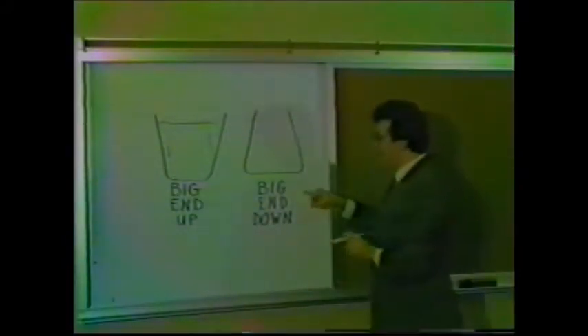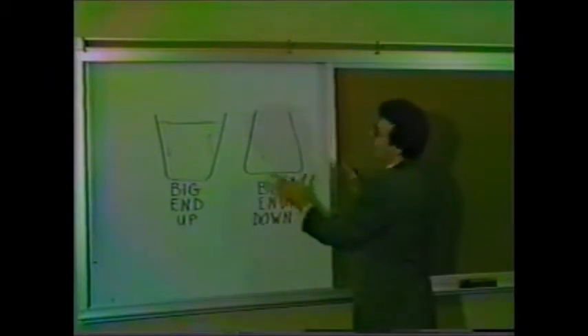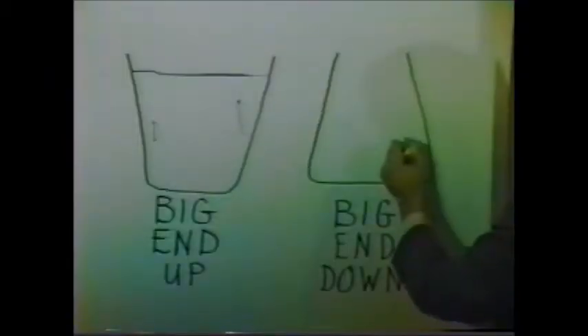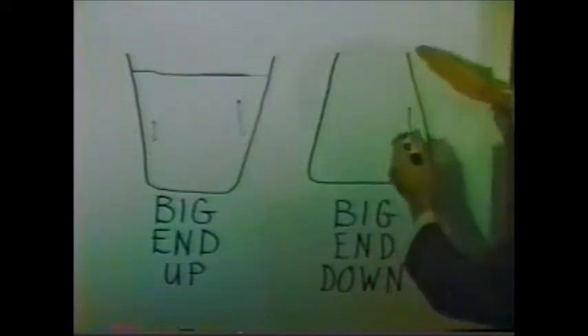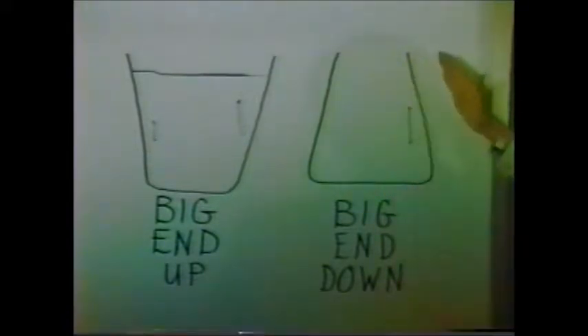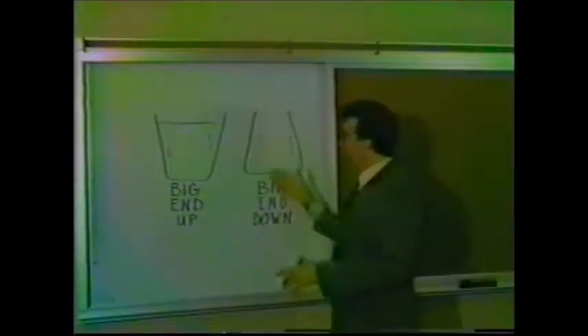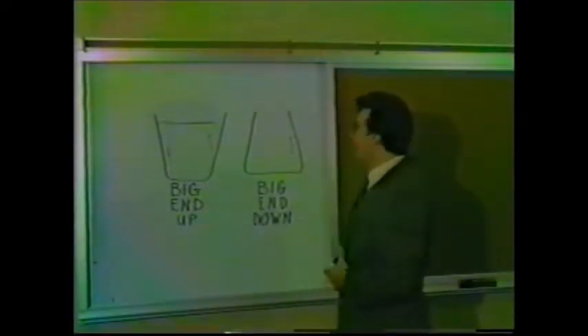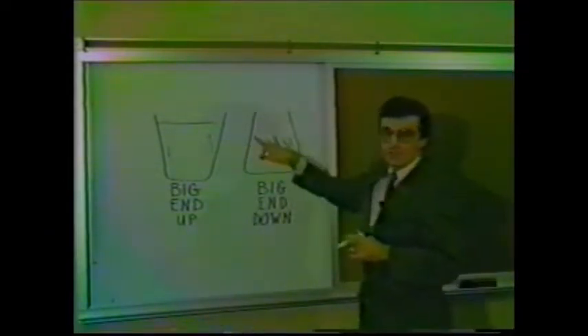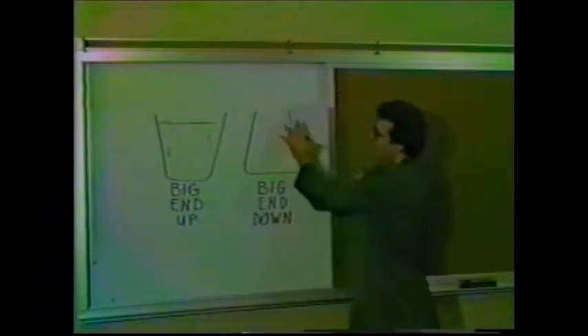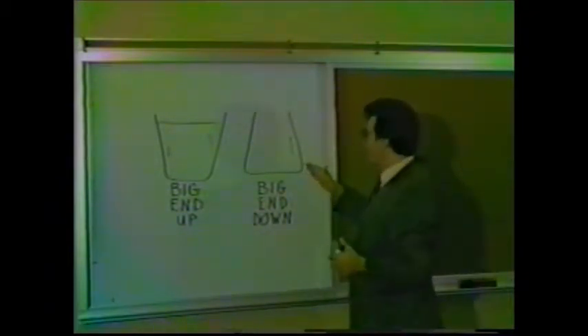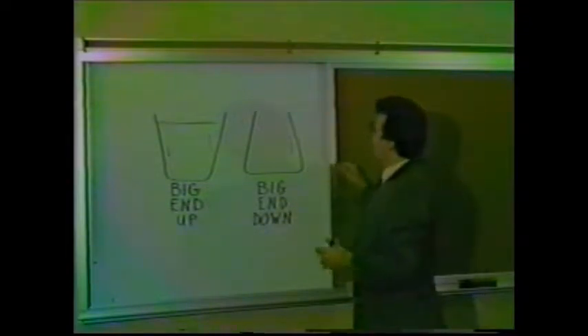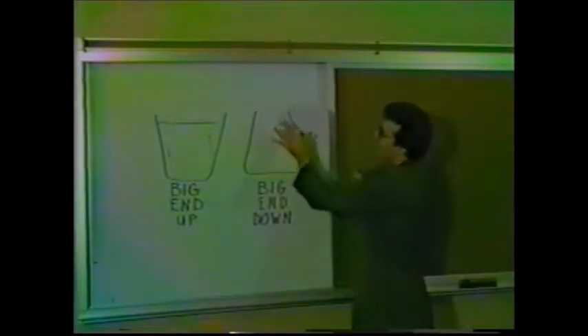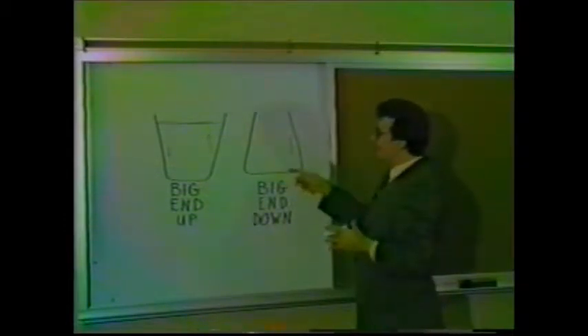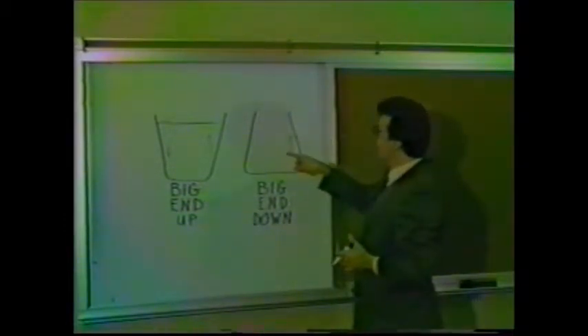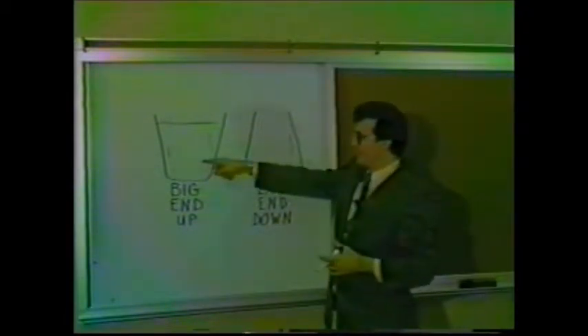Contrast that with big end down ingot molds, where bubbles that start to form and float up can actually become trapped at or near the surface of the ingot. Well, you say, good grief, then why don't we just get the big end up and be done with it? Well, it turns out that there are other costs associated with these two things. A big end down ingot, or the product of a big end down ingot, is actually lower cost. The reason is that after the steel has solidified, it's easier to strip the solidified steel out of a big end down ingot than it is from a big end up ingot mold.